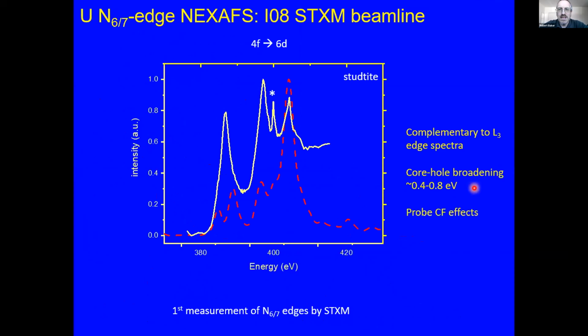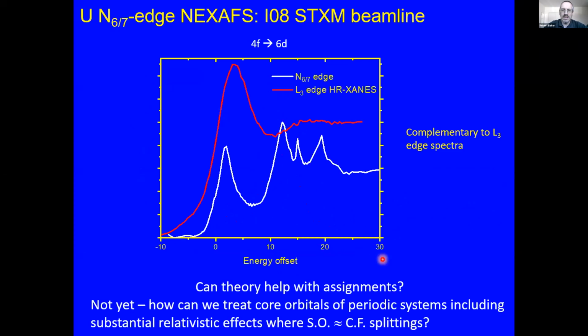But going back to our experiments at Diamond, what was really nice is we could look at the soft edges. So this is the N6-7 edge. So this is the transition from the 4f to the 6d. This, I think, is the first time anybody's measured this by STXM technique, and it should be complementary to the L3 edge spectra because it ends on the d state. Much less core hole broadening, so maybe we could use this to probe crystal field effects. This red dotted line is the theory.